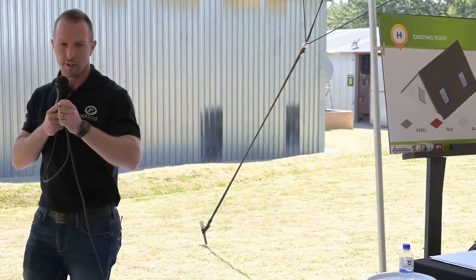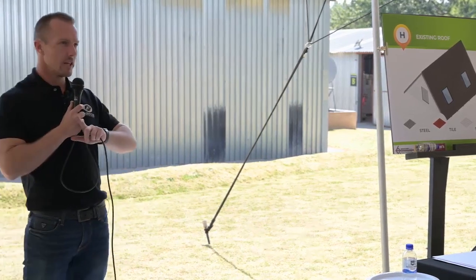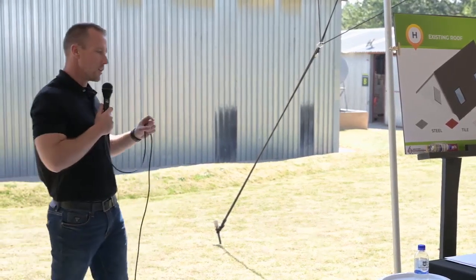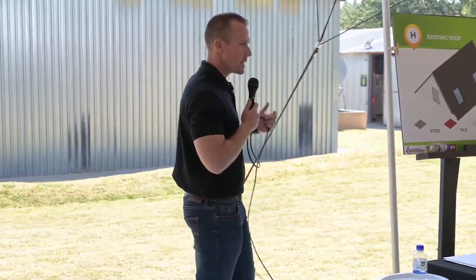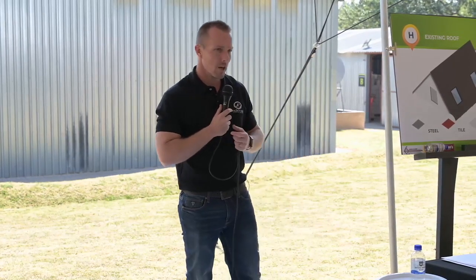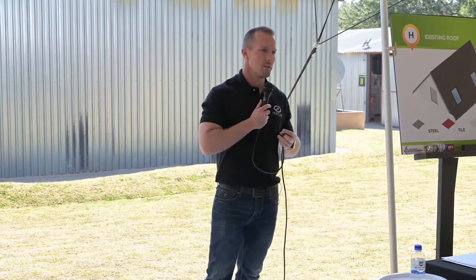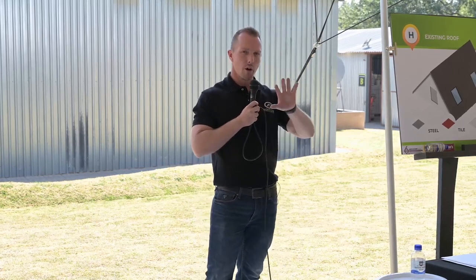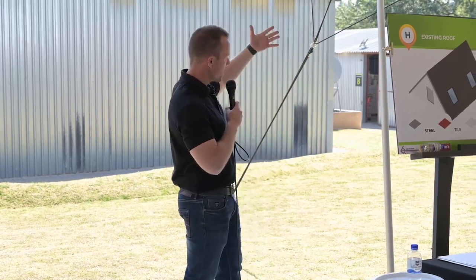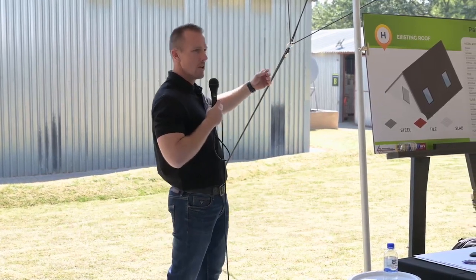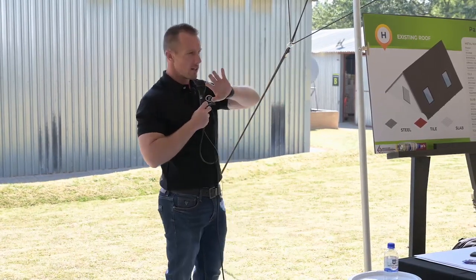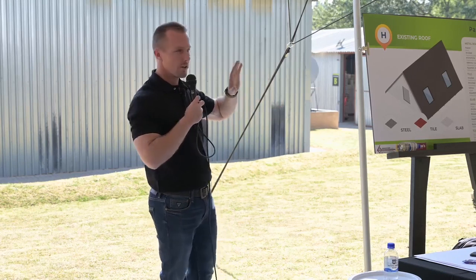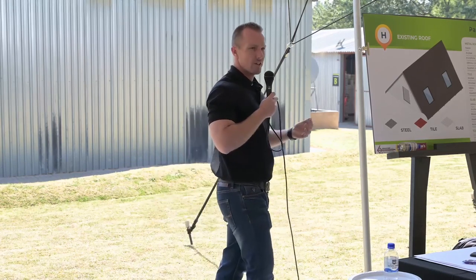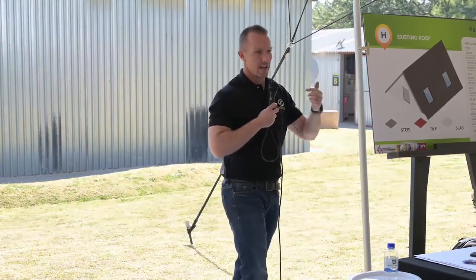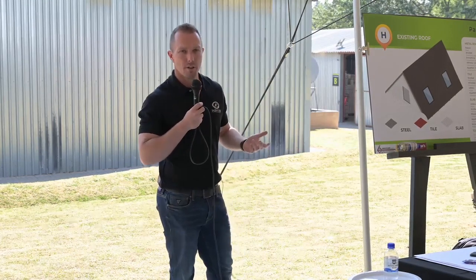And what you find is the film that our EnviroPrime makes is a totally sealed and complete film, which is different to what we look at when testing, because what we find with a lot of our competitors' water-based rust-inhibiting primers is they're full of pinholes. So if you hold it up in the sun on a sheet of glass, which is the test that we do, you're going to find that there are, in sometimes, millions of pinholes across this film. So what good is that, right? If the water can get through these holes, it's going to get to the steel. So why even prime it in the first place?